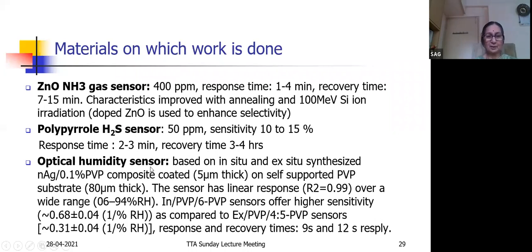Then we have worked on an optical humidity sensor, which is based on in situ and ex situ synthesis of Ag nanoparticles, silver nanoparticles, and PVP, polyvinylpyrrolidone, and we have made a composite. We coated a 5 micrometer thick film on a self-supported PVP substrate. And the sensor has a linear response from 6 to 94%, and it offers a sensitivity of 0.68 per percent RH.